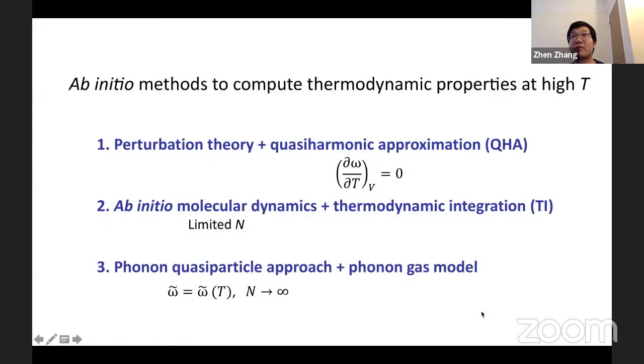Here are some ab initio methods to compute materials' thermodynamic properties at high temperatures. Perturbation theory plus the quasi-harmonic approximation has been successfully applied to various weakly anharmonic systems. The quasi-harmonic approximation neglects the intrinsic temperature dependence of phonon frequencies and treats phonon frequencies as explicitly volume dependent only. However, this method fails for strongly anharmonic systems with imaginary phonon frequencies or strong intrinsic temperature dependence of phonon frequencies.